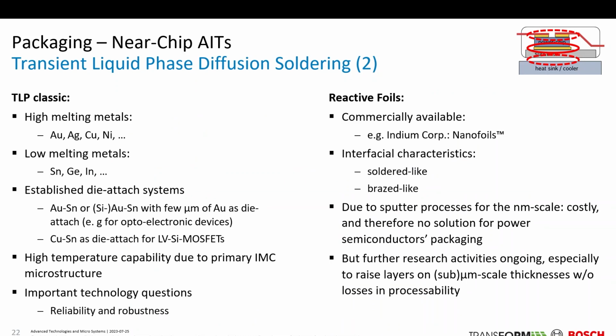So here, in comparison to each other, for this more or less classical way, you can use a variety of high melting metals, shown here, as well as for the low melting systems. You find such solutions in well-established die-attach systems for optoelectronic devices, for example. And I would say Infineon has a solution for low-voltage silicon MOSFETs as well. The high-temperature capability and high-loading situation on such a joint is given by the primary IMC microstructure. So important technology questions are always the reliability and robustness of such a defined and generated joint.